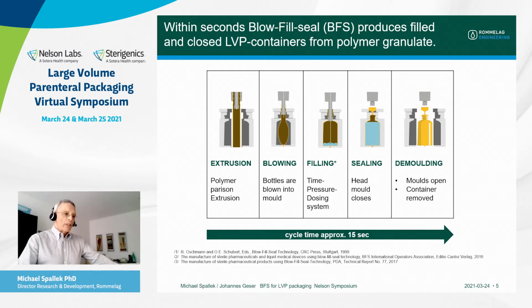demolding. The mold opens and you can remove the container and put it into the next steps like inspection or labeling. Very importantly, it is to be noted that the cycle time is approximately 15 seconds only. So from a rigid polymer granulate into a filled closed container, it takes just about 15 seconds. And of course, we do need sterile blowing air and sterile filtration for the formulation.